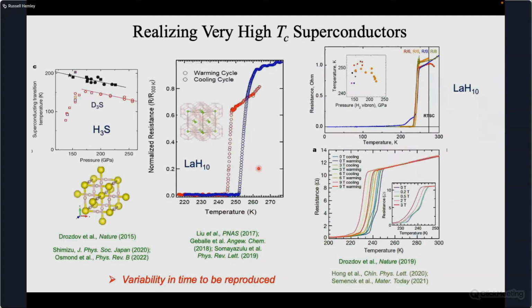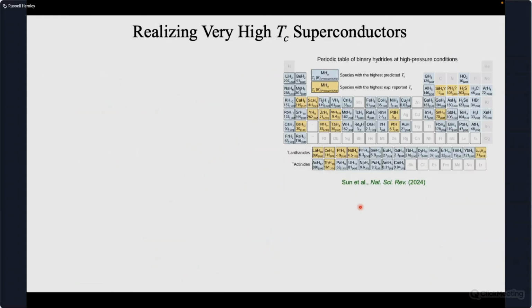Another aspect, as I mentioned, is that these papers confirmed these predictions, but the subsequent confirmation by experiments had been a problem. It took something like 5 or 6 years for another group to confirm the results for H3S. In contrast, Eremets' group confirmed, within a few months of our announcement, the superconducting transition in this novel compound LaH10, with very nice measurements, including additional magnetoresistance measurements that support the superconductivity.